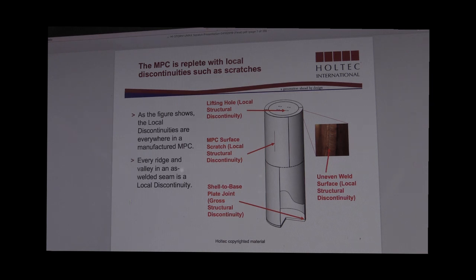And the slide also points out an example of a gross structural discontinuity, which is at the bottom of the MPC. This is sort of the classic example where you have the shell to base plate joint, where you have a 90-degree corner. And what differentiates a gross structural discontinuity from a local structural discontinuity is that gross structural discontinuities affect the stress through the thickness. And they're typically uniform throughout the shell diameter. So that's why something like the shell to base plate joint is a classic example of a gross structural discontinuity.